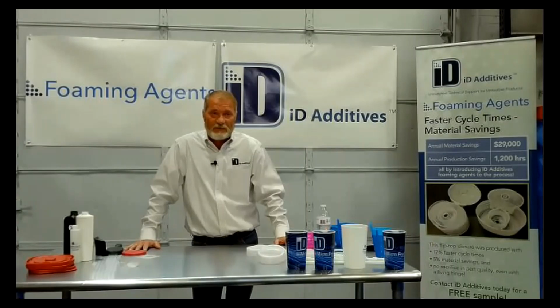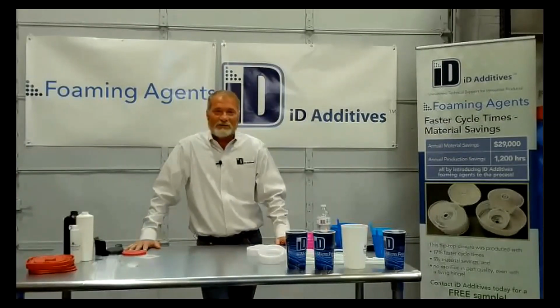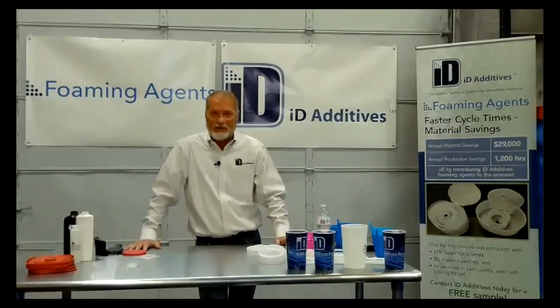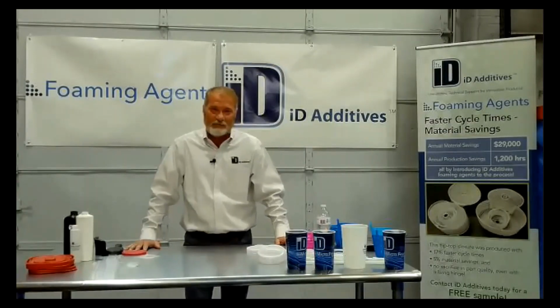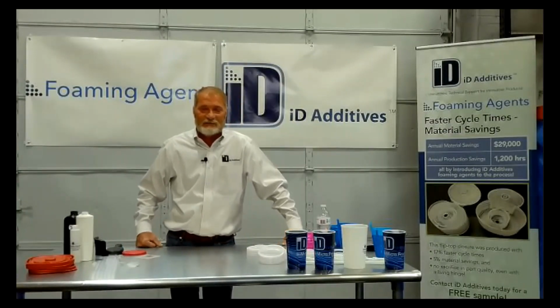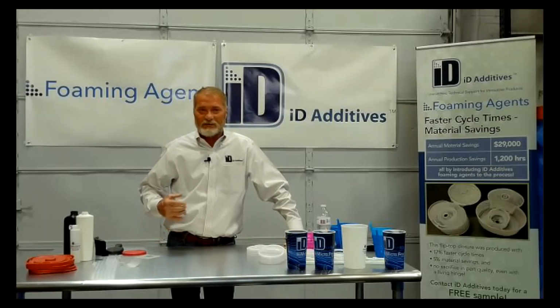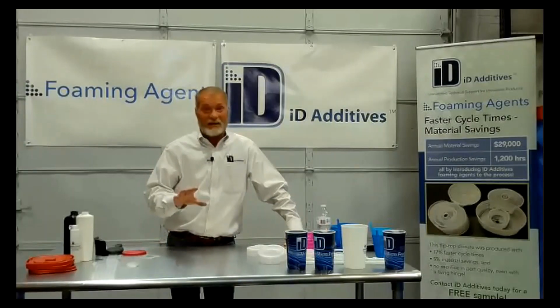Another question came in. Do the foaming agents have any strong effect on colored parts? Actually, it'll make colored parts darker sometimes. A lot of people have dispersion issues with color and things like that, but you add a little bit of foam with that, and it'll disperse that color extremely well. I mean, even with a GP screw without a mixing screw, it does a very good job of mixing it, only because it drops that viscosity down to where it mixes really well. I've had colors actually look better with foam, on the aesthetic end.